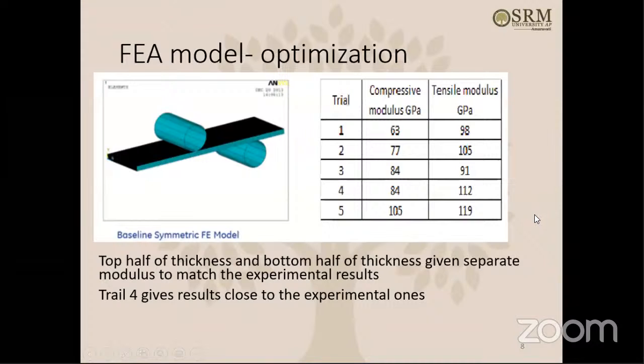So then the FEA model. There's some disturbance. Yeah, so for the FEA model, we tried to optimize it. We took the half thickness of the FEA model, the top half and bottom half, and varied the compression side modulus and tensile side modulus to try to match the results. That's just one way to match the experimental results with FEA, and that's what we did. We found that trial 4 is giving good results, so that's what we use for further calculations. Okay.